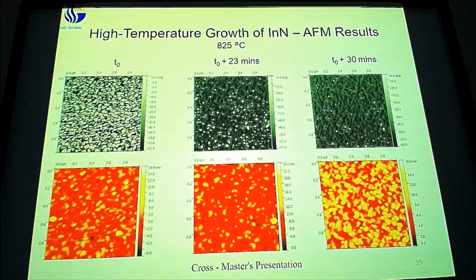So I took my sample out of my machine because I saw that it was doing this, and I grounded it. I took a wire, I literally soldered it to the top of the sample in order to get an electrical connection from the sample to the ground. And I let some time pass. So at T0, which at this point means absolutely nothing, it just means the first time I got it back into the machine after I soldered the wire onto it, it looked like this. As time went on, you can see that my phase changed. I actually changed something with the interaction between the sample and the tip to make a better AFM picture, to cause less interaction with my sample.